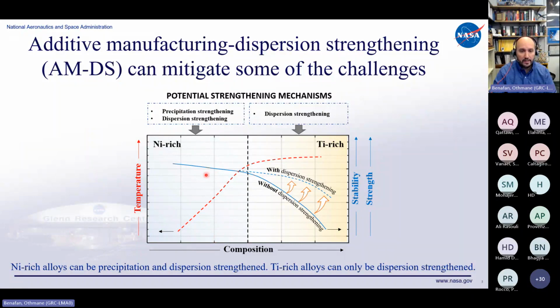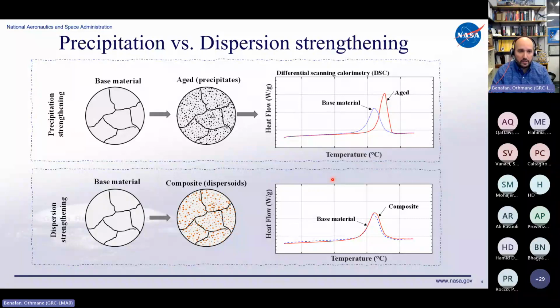The blue line basically identifies stability, and as you go into the titanium-rich region, stability is lowered because you don't have a strengthening mechanism. And when you go to the titanium-rich side, you can see here, follow the red line, that the temperatures increase. Sometimes we're interested in high temperature activations, but we have to compromise and go slightly nickel-rich, lowering it, because of stability. Well, what if we can keep the transformation temperatures high and increase the stability via dispersion strengthening? So this is the whole idea, is to keep the chemistry intact, like this cartoon shows here.